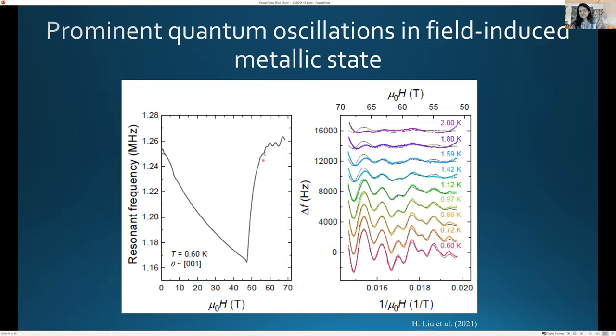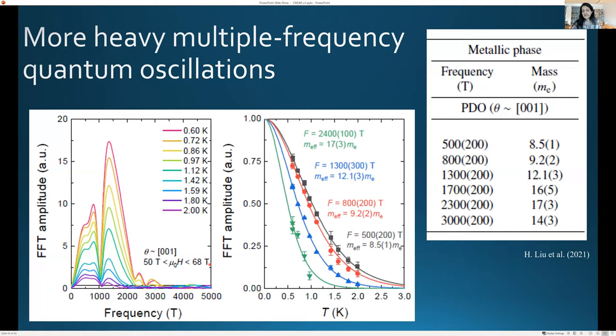So unlike the case of the SmB6, which shows no sign of metallization, the magnetic torque and electrical resistivity sharply change at around 50 Tesla, and you can see the quantum oscillations become much more prominent here. And so this is now in the metallic state, which we know and love. So in this state, again, we look at the amplitude as a function of temperature. And interestingly, we still see small frequencies and heavy masses.